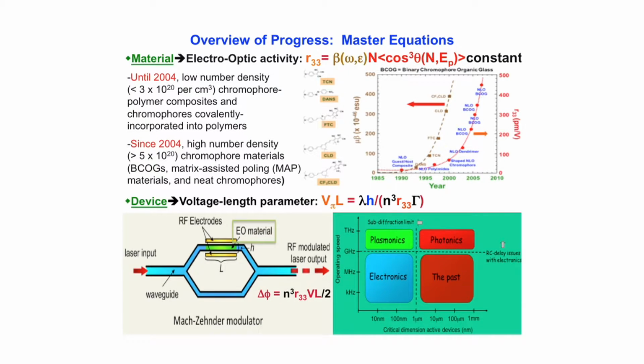Now, I'd like to move on to this figure, which talks about the three fundamental carriers of information: electrons, photons, and plasmons. Electronics permit very small devices, but the operating speed or bandwidth is not very good. The reason is that electrons have strong electron-electron interactions, and so there are resistive losses in transmitting electrons through metal wires. Photons, on the other hand, have essentially no interactions, and so very high speeds can be achieved, but until recently, critical dimensions for photonic devices were limited to about 1 micron. Plasmonics permit both high speed and short size, but the losses for plasmonic propagation are very large, and the only way they're going to be feasible is if you can go to very short devices.